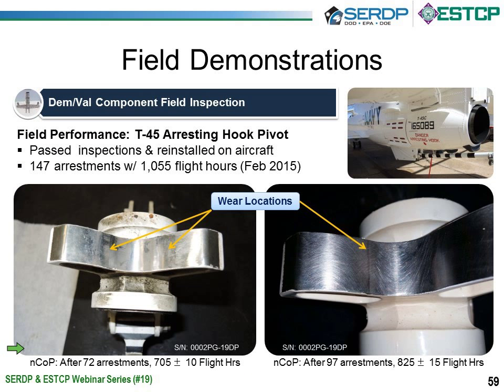As we went into the field, this upper photograph shows the back end of a T-45 aircraft. This is the arresting hook, and right at that interface is where the arresting hook meets this cam face. There's a great deal of loading and wear, both due to vibration in flight and shock loading if the aircraft lands off axis and the arresting hook has to shift to its side position. What we've noticed here, this is the cobalt phosphorus demonstration component after 72 arrestments on carrier and 700 flight hours. And we have another illustration at 97 arrestments and just over 800 flight hours. There's a little bit of wear occurring in this face, and this is what we're trying to prevent.